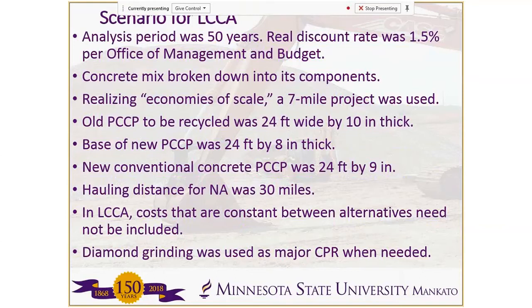The old concrete pavement that was to be recycled, we assumed was 24 feet wide by 10-inch thick. And the base of the new concrete pavement to be placed was 24 feet by 8-inch. And the new concrete pavement was assumed to be 24 feet wide by 9-inch thick. For a haul distance for our analysis for the natural aggregates, we assumed 30 miles.